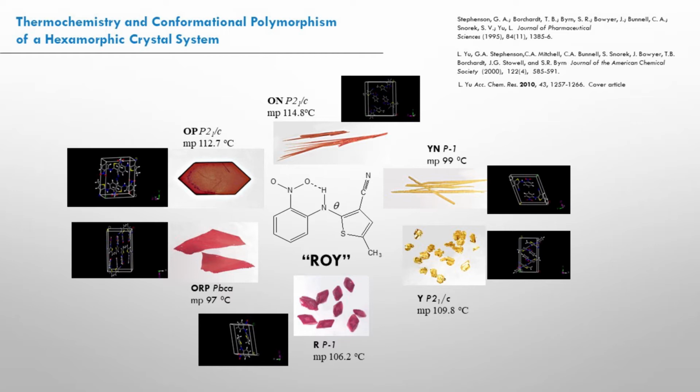It's the same chemical entity in different arrangements within the crystal lattice. We did the crystal structures of all of these forms, and the arrangement of the molecules was different. And also, the color was associated with the planarity of the aromatic rings. But it shows you very well how different substances can be, just based upon the packing within the crystal lattice.